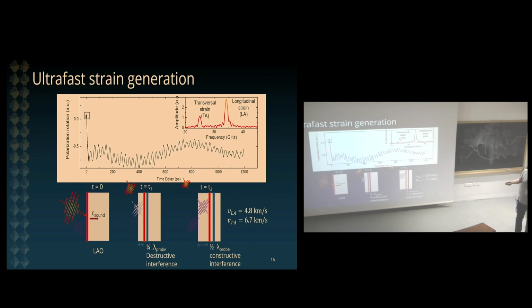It's a pump-probe type of experiment. We come with a second light pulse that is reflected both by the surface of the material and by this propagating wavefront. As these two light probes are reflected, they undergo destructive and constructive interference as this object propagates inside the material. Every time a quarter wavelength of the probe is propagating inside, we have an interference fringe. So we can follow the propagation of this mode for a long time. That's one of our data sets.